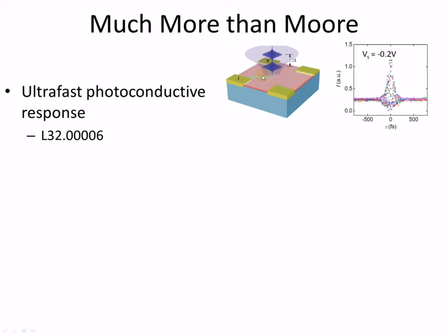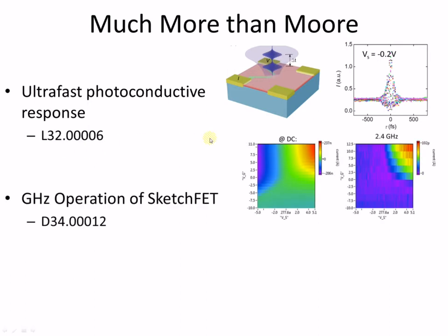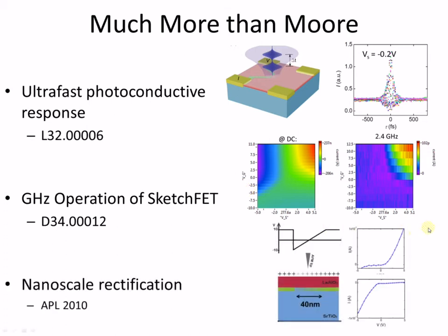Recently we developed a photoconductive switch and have been using this in an ultra-fast mode to generate nanoscale or molecular scale terahertz pulses. This is a talk that was also given at the APS March meeting. As I mentioned before, we have demonstrated that these sketch FETs can operate in frequencies in excess of gigahertz. And we have also demonstrated that by changing the voltage profile along the wire, we're able to create rectifying regions that mimic the behavior of Schottky diodes.